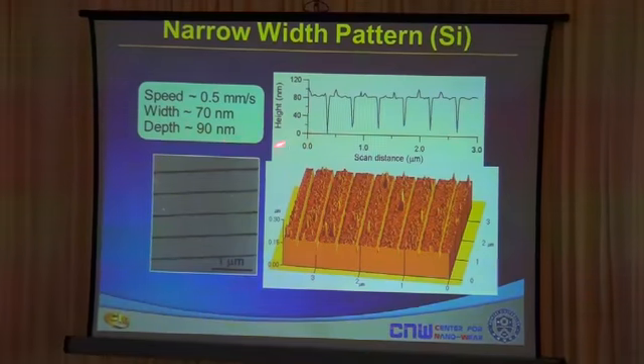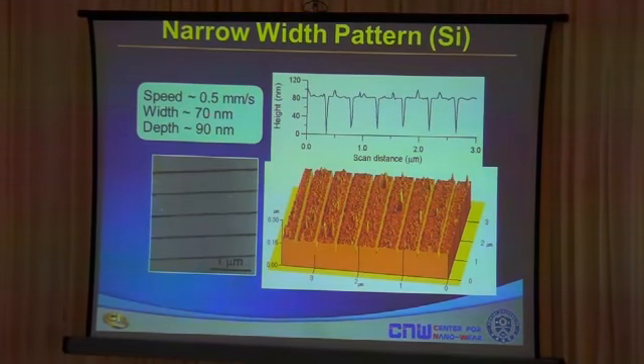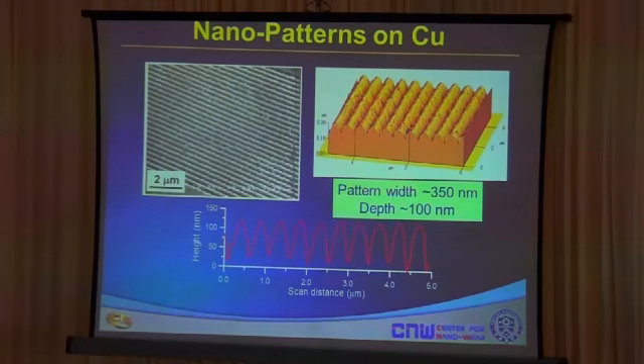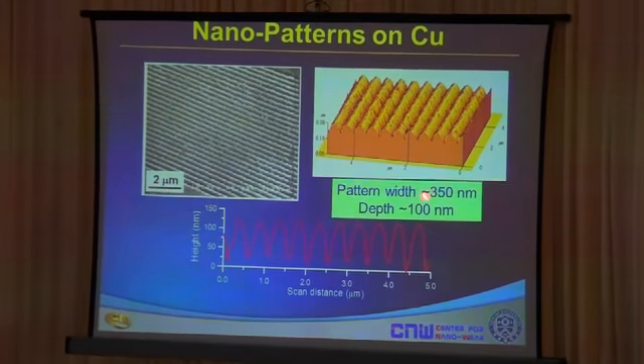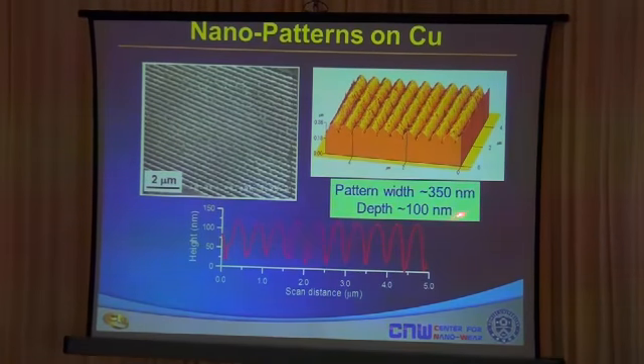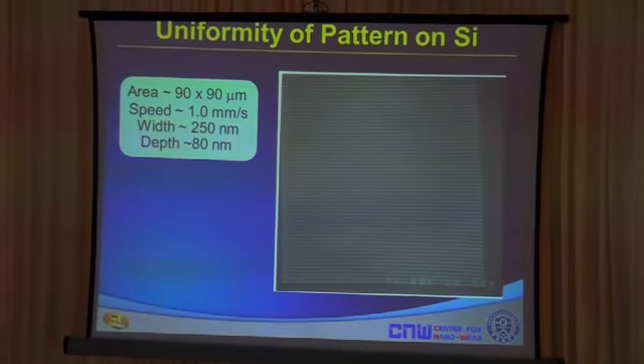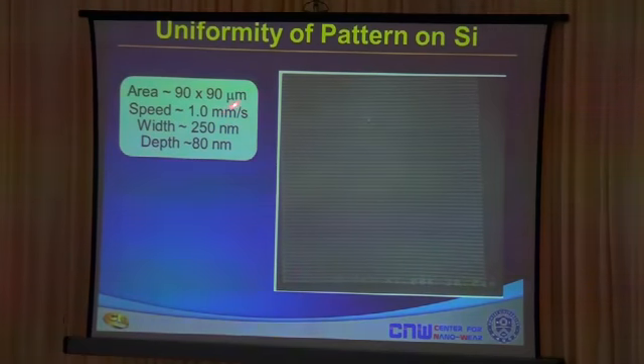Not only can you do that at 250 nanometers, but if you control the process very well, we're able to reach down to about 70 nanometer grooves on silicon surfaces. And not only on silicon surfaces, we're able to do that on metal films as well. We're able to make these fine patterns on copper with a pattern width of about 350 nanometers, a depth of about 100 nanometers. We're also able to do this over a relatively large area, over 90 by 90 micrometer scanning, on silicon. We're able to do this on copper as well.